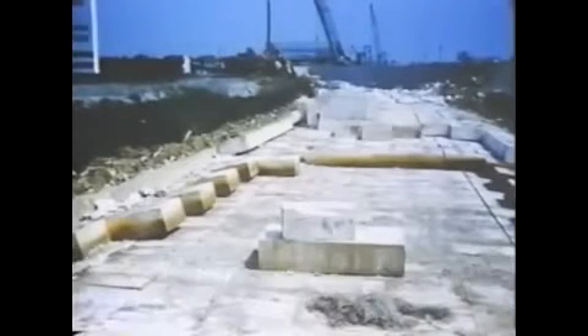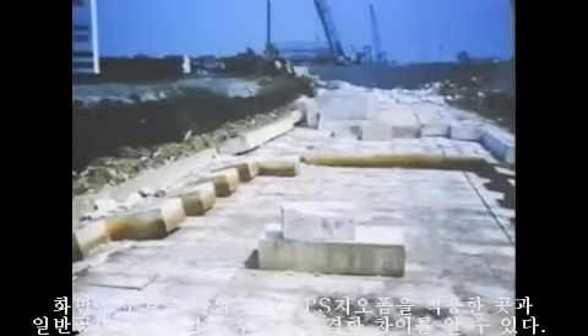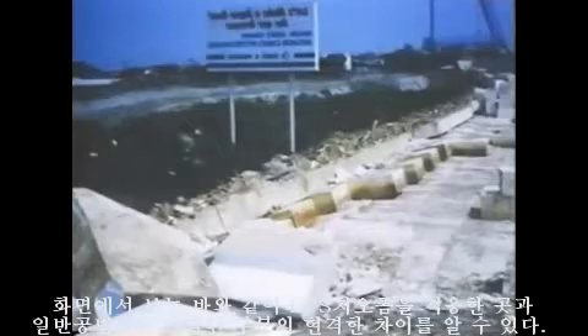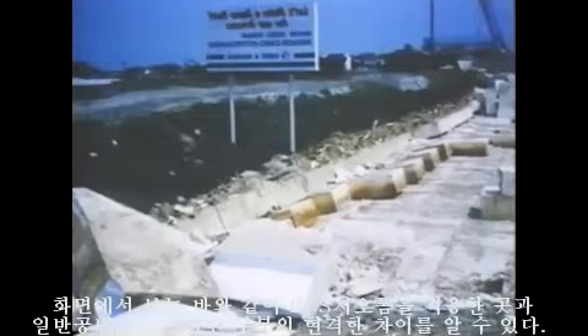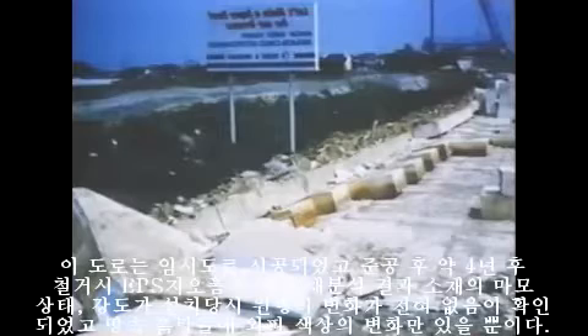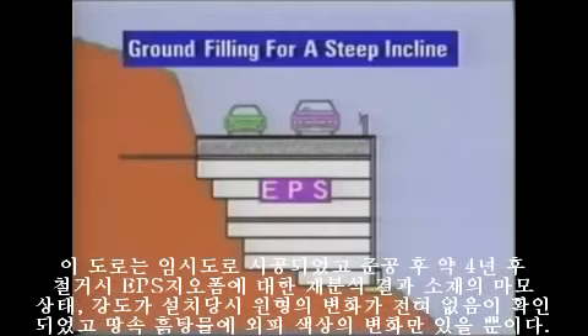At the time of removal, a study was conducted on the foam to determine if there was any deterioration in the EPS blocks. Testing showed that the performance properties of the material had not changed since installation, and no deterioration had occurred over the 4-year period. There was discoloration of the blocks due to subterranean water.